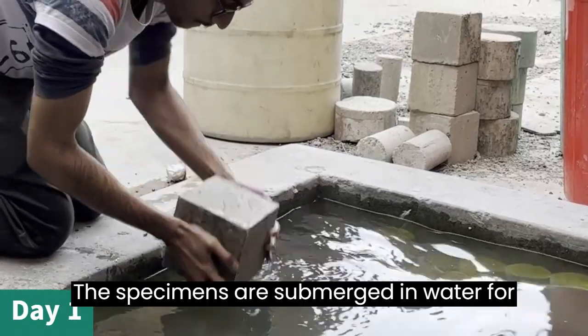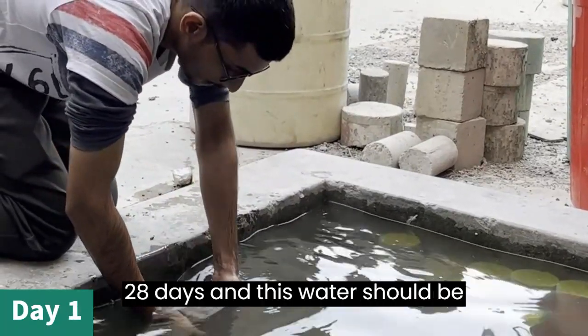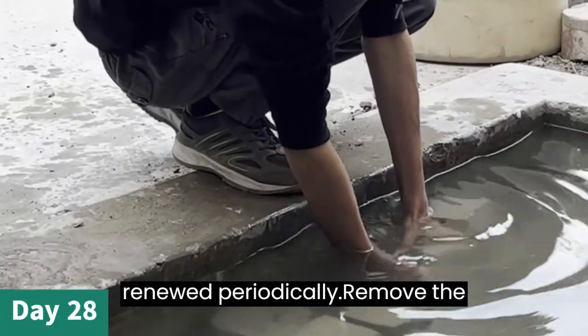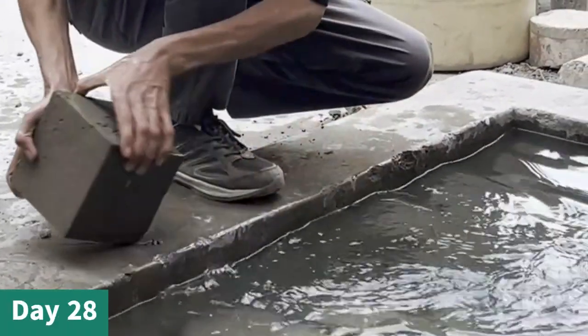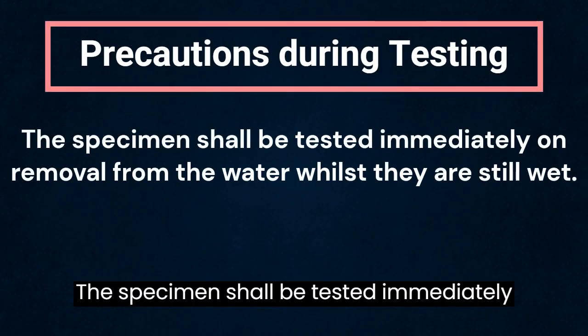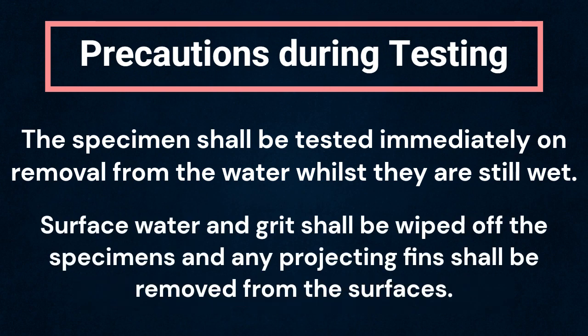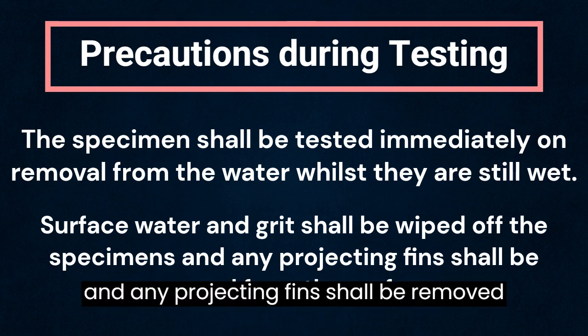The specimens are submerged in water for 28 days and this water should be renewed periodically. Remove the specimen from water on day 28. The specimens shall be tested immediately on removal from the water whilst they are still wet.